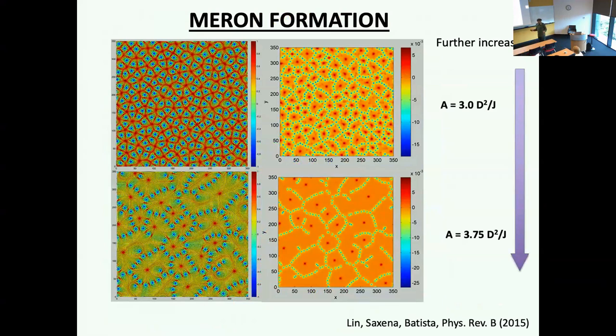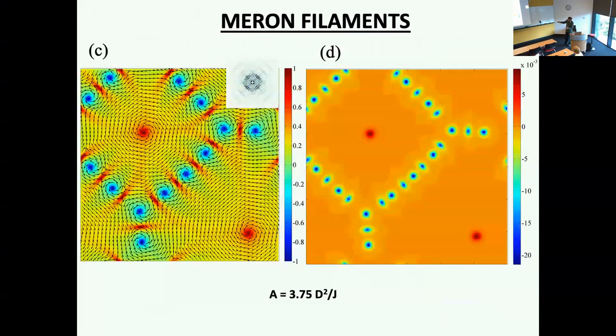So now what you get, these blue dots, if you can see, are half skyrmions, called merons, and red dots are antimerons. So you get filaments of these merons, each containing an antimeron. And this is very interesting. If you want to see how this spin field is doing, again, blue and red are color for the Z component of spin. And so here is a meron. It only covers, so spin starts like this, and it becomes horizontal. That's it. So it covers this sphere only half. It doesn't go fully. So the blue things are merons, and this is the opposite vorticity or helicity, whatever you want to call it, antimeron. And these things are very important.